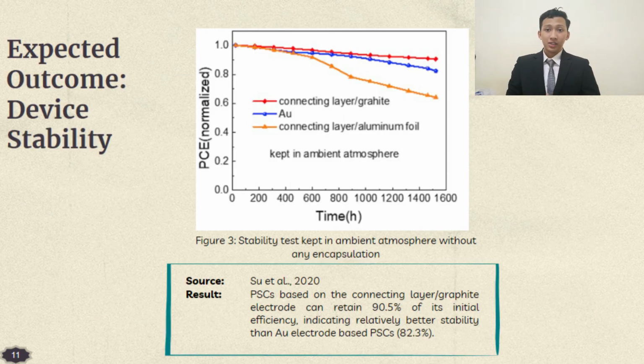In terms of device stability, Figure 3 shows the result of stability tests from a previous study. Perovskite solar cells based on carbon graphite electrodes can retain 90.5% of their initial efficiency, indicating relatively better stability than Au electrode perovskite solar cells, which retain 82.3%. This high stability of perovskite solar cells is due to the ion diffusion resistance and hydrophobic property of the carbon films. Thus, in this research, incorporating the RGO-MoS2 electrode is highly expected to improve the device stability as well.